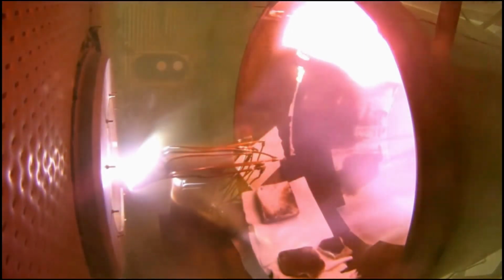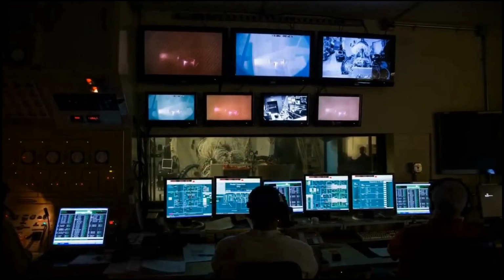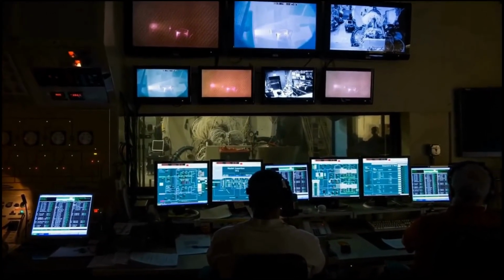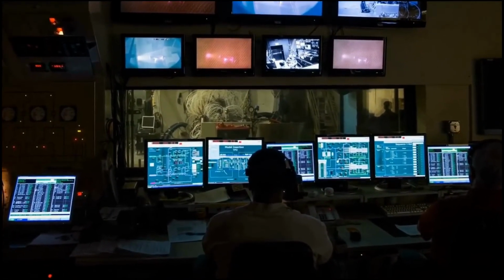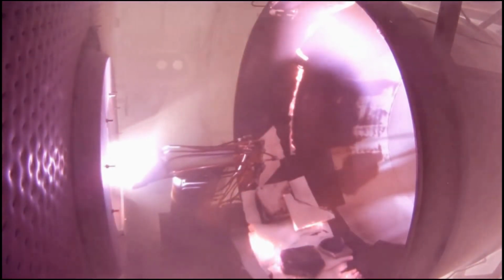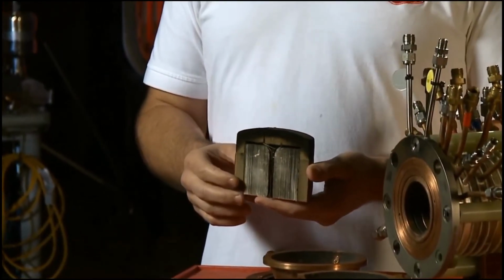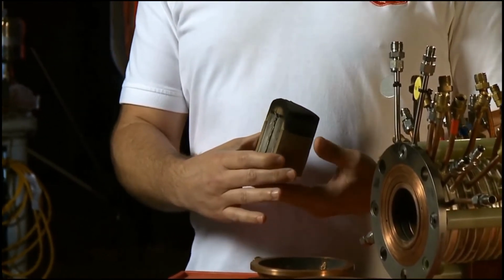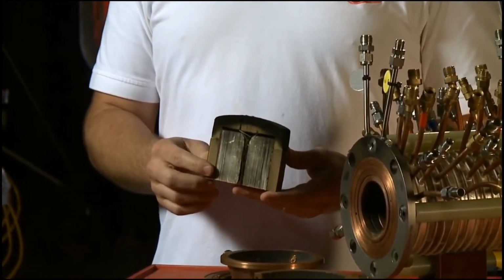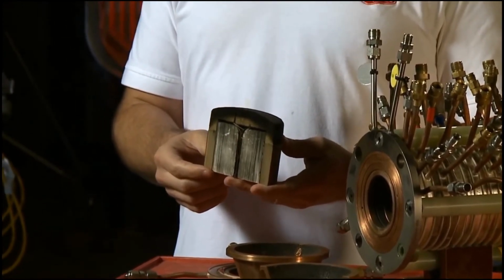During the test, we get all kinds of additional data. We would test these types of ablators, typically up to 3,000, 4,000 degrees Fahrenheit, even higher. We would test them at very high temperatures for different types of trajectories, primarily for the lunars, which gave the highest heating rates and correspondingly the highest temperatures at the surface of the model. For an ISS type of reentry, the heating rates are a lot lower, so we're talking about 2,000, 3,000 degrees, but for a lunar type, very ballistic type of reentry, you're about 4,000 degrees, even higher than that.